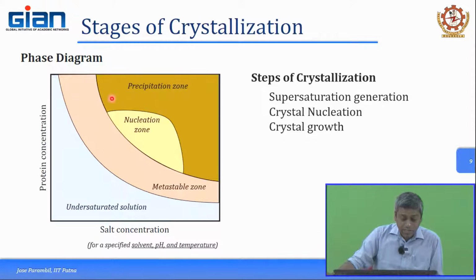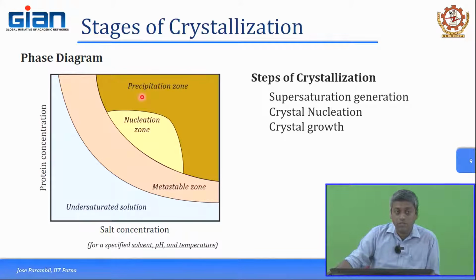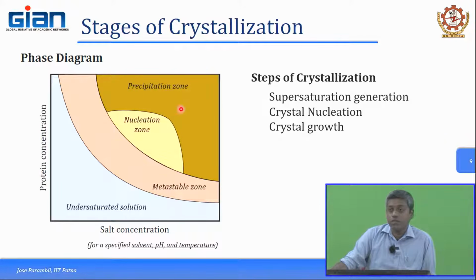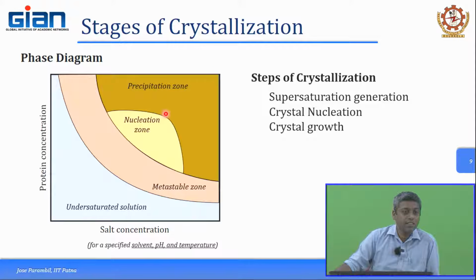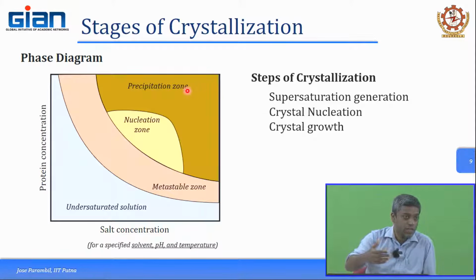Now, it is interesting to see that in protein crystallization with salt, you often see quite a lot of region which is nothing else but a precipitation zone. Now, what do you mean by precipitation? It is very low solubility, and the proteins or these molecules just start to precipitate and form solid material. But this solid material might not be crystals. These are not crystalline material. They are typically in the precipitation zone.